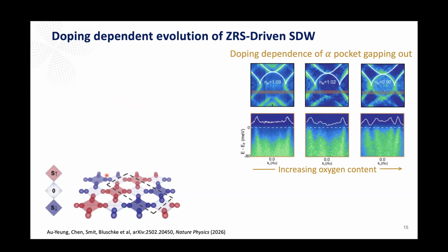To show this, we can use our tight binding model, but extend it to a supercell of the spin density wave. So now I'm not showing the oxygen and the nickel, I'm only showing the oxygen orbitals. And to mimic the spin density wave, we put a very small magnetic moment on plaquettes of oxygen orbitals.